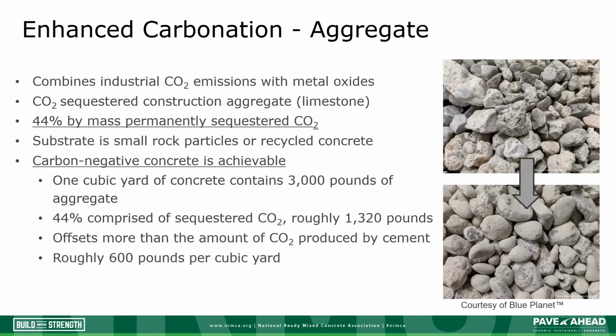Enhanced carbonation can also be applied to aggregate production. Carbon sequestered aggregate consists of a coating of calcium carbonate, synthetic limestone, crystallized on the surface of recycled aggregates, such as crushed recycled concrete, giving it a smoother surface finish. Using carbon sequestered aggregate can offset roughly 600 pounds of CO2 per cubic yard. Again, looking at our previous example of embodied carbon per cubic yard of concrete, that's more CO2 than is attributed to the initial cement production.